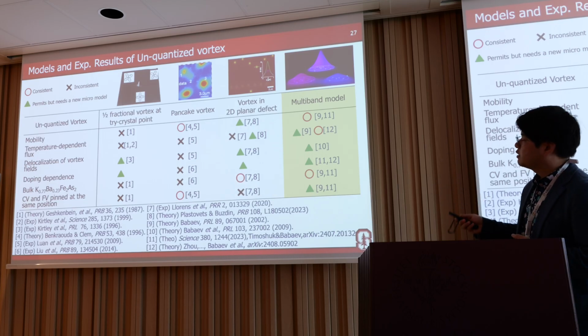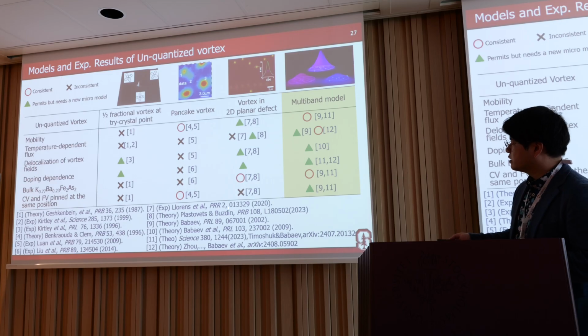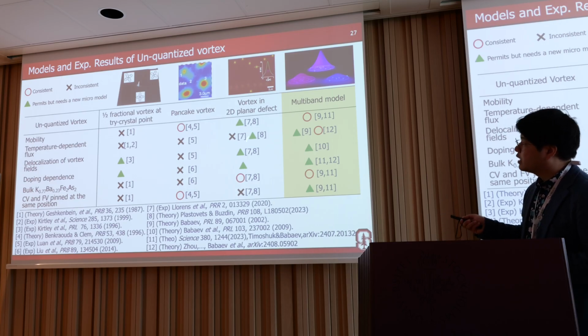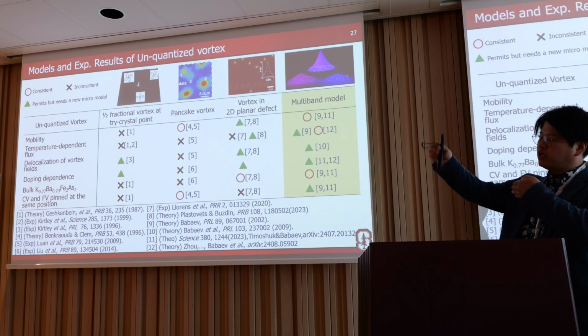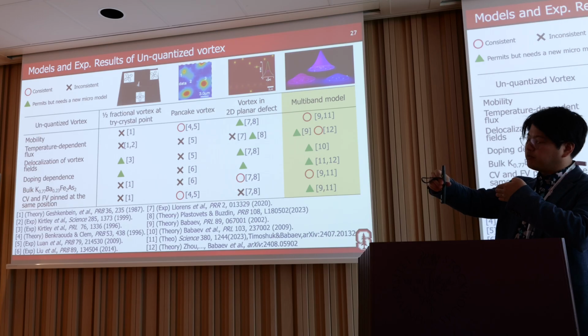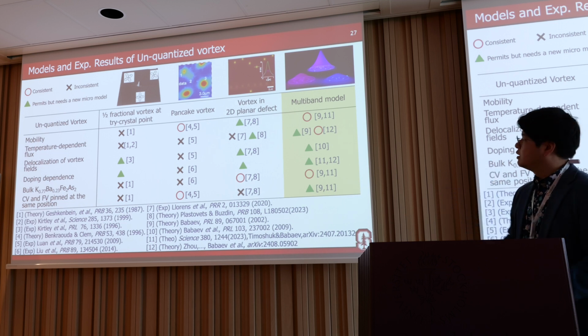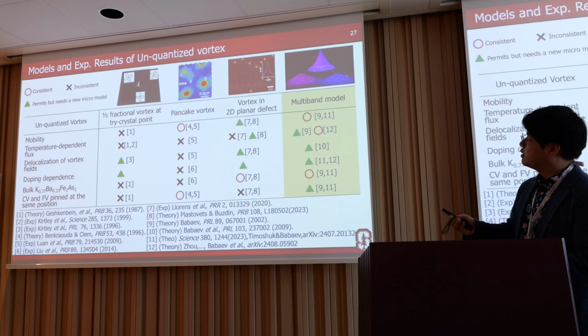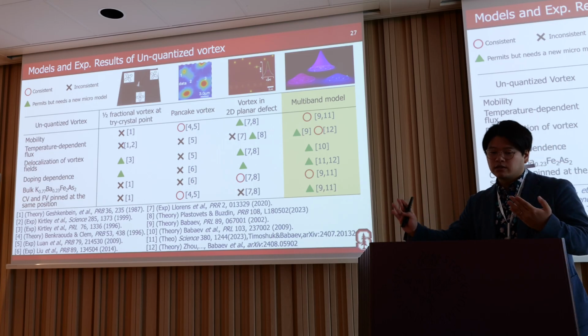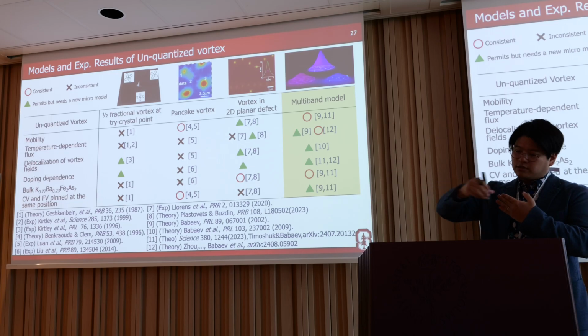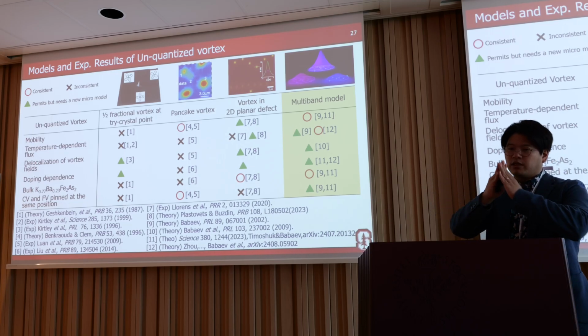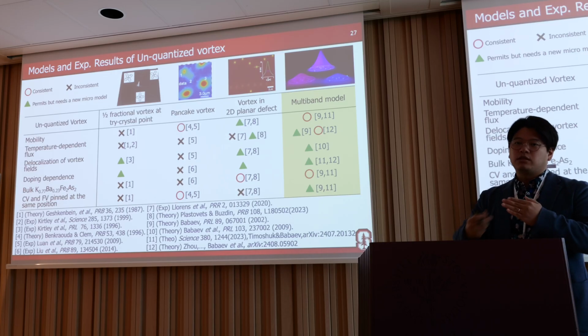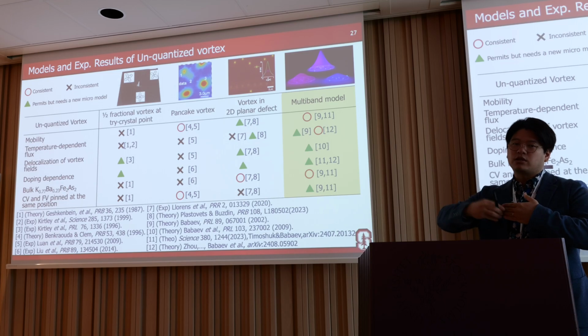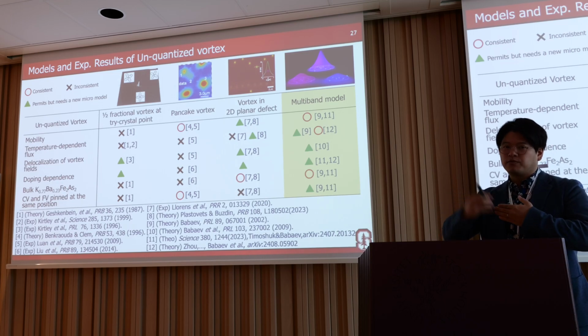And after our publication, Plastovets and Buzdin proposed this model to explain the temperature dependence also, where the pinning location is very temperature dependent. At lower temperature the vortex is closer to the planar defect and is more delocalized. But it is still inconsistent, because there is always a 2D planar defect there, and when the vortex is close to that defect, the vortex should always be very delocalized. But in our case, we see that the integer vortex and the fractional vortex are at the same location, in different cooling cycles. It cannot be explained with this theory.